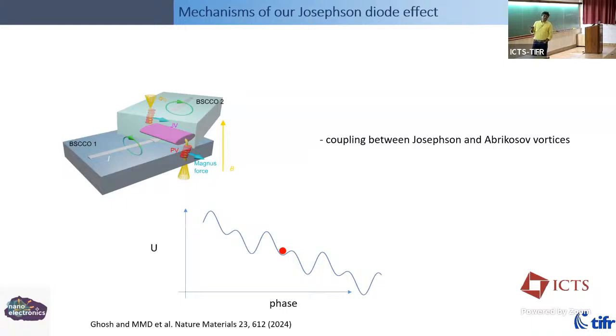A kind of phase picture of thinking about this Josephson junction is that if you have a current phase relationship which has higher order components, so it's not just I proportional to sine phi, but some other terms like sine 2 phi or even higher order, your current phase relationship, or the potential rather, will have these other higher harmonics. And if you look at this cartoonish picture here, if your system lives here, the barrier for it to overcome this potential is different from the other, and that's why you see this asymmetry or the diode-like response. And this also explains why the switching distribution on positive current and negative current is vastly different, because the barrier that it sees is very different from two sides.